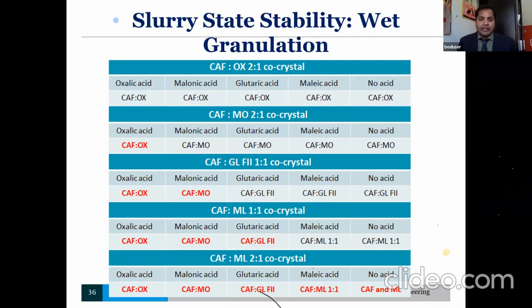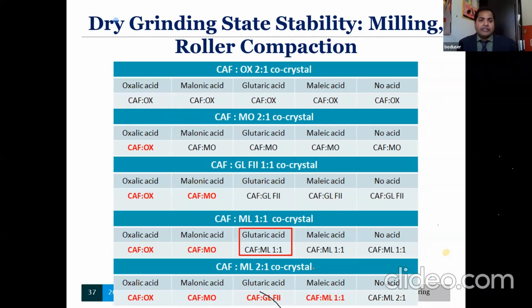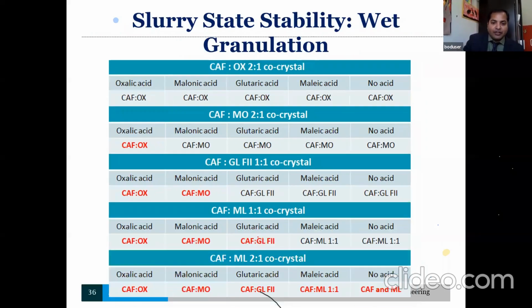So what I would like to summarize from this work is, based on the interactions that the co-former is going to play around the co-crystal in the formulation conditions or processing conditions, it is going to significantly impact your co-crystal integrity. This is continued studies with the dry grinding, where I will draw your attention to this particular example only. When caffeine and malic acid is taken and impacted with the glutaric acid, here glutaric acid is still there. Whereas in this one, glutaric acid has replaced.